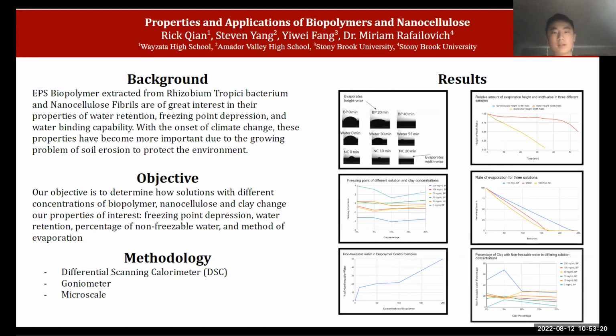Finally, moving on to the bottom left, our DSC results show the non-freezable water percentage versus concentration, indicating that the higher the biopolymer concentration is, the more non-freezable water is present, as more biopolymers can bind to the water. Furthermore, in the graphs with the non-freezable water percent versus clay percent, clay is shown to have little significant effect on the percentage of non-freezable water. However, it still shows that higher biopolymer concentrations generally have more non-freezable water, as previously stated.